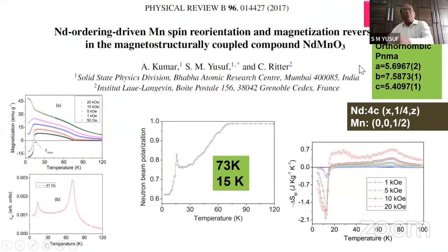This we have observed, for example, in this perovskite NdMnO3. Here you see the magnetization as a function of temperature at different fields. At lower field, you do see negative magnetization, but at higher field, it remains positive. AC susceptibility also shows the signature of phase transition, both at the magnetic ordering temperature from paramagnetic to ferrimagnetic, and also at the compensation temperature. Neutron depolarization study also gives the signature that at the temperature where this polarity reversal takes place, there is a recovery of neutron beam polarization. I will be touching upon this part in more detail in the next example.